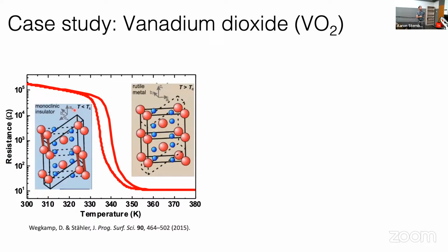So vanadium dioxide is a correlated electron system. It goes through an insulator to metal transition at a temperature of around 340 Kelvin. And together with this electronic transition, there is a structural transition from a monoclinic structure to a rutile structure that occurs around the same temperature. There's sort of a chicken and egg question, which has been studied for decades now, of if it is the electronic transition that drives the structural transition, or if it is the structural transition that drives the electronic transition. And various perspectives have been given on this problem.